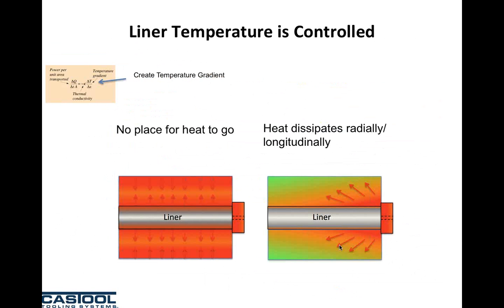So we talked quickly about a diametrical gradient. Basically, by moving the heating elements close to the liner, we get a diametrical gradient. So if our billet was 860 degrees, we would like our liner to be maybe 800, 810, the outside of the container maybe 400, 450, and our container housing 250. That's our diametrical gradient. We also want to have a longitudinal gradient.